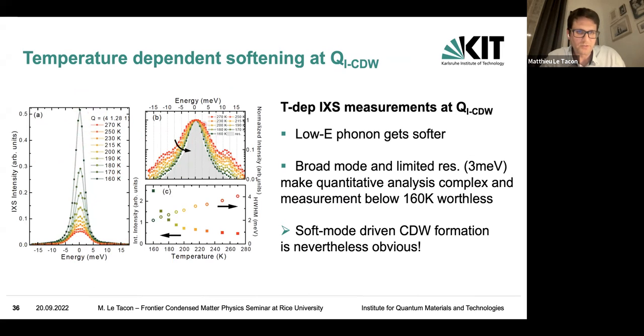But if you plot that on log scale and normalize, you get the phonons here, and you see that there is a phonon which is soft but not completely soft, and that it's getting softer and softer as you cool down. A way to quantify that is to plot the half width at half maximum of this profile, and you clearly see that it decreases while the intensity just shoots up here.